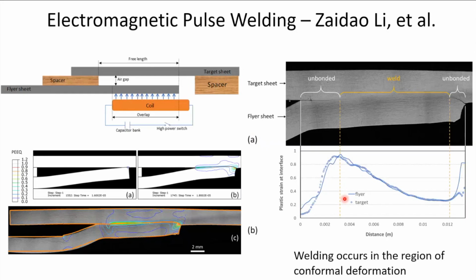So the next and the final part is about my recent work here at Brunel around something which you can regard as a process between cold spray and explosive cladding, because in terms of the variation in geometry or impact angle, I think it's closer to cold spray, but in terms of bonding it is very close to explosive welding. So basically, here, instead of using explosive, we use electromagnetic acceleration. This is something called EMPT that we have at Brunel. We look at this together with colleagues led by Zaidao Li, who's now in Stellium.